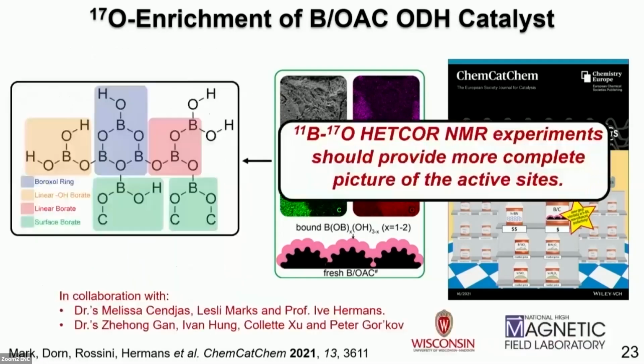Now, from boron NMR spectroscopy, we were able to show that about 80 to 90% of the boron is completely clustered on this carbon surface. However, we don't have a good understanding of these borate species. And what I mean is whether we have linear borate groups, if we have borates within a ring, and the relative population of hydroxyl groups throughout this layer. So here we're going to utilize oxygen NMR, and in particular these boron oxygen experiments, to really build a complete picture of what this active site looks like.